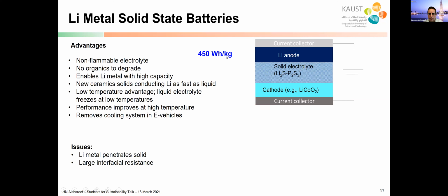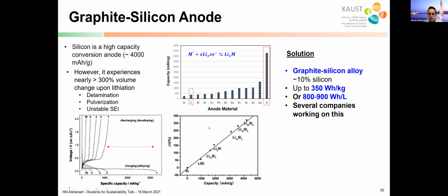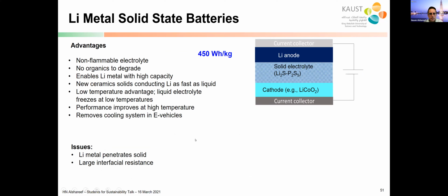Solid-state battery could give 450 watt-hour per kilogram. This is also realistic. Here you use a solid electrolyte, a ceramic electrolyte. It's non-flammable. There's no organics to degrade. And this will allow you to use the lithium. And the lithium, if you look at this, also actually, it's not in here, but it has a very large capacity as well, just like silicon, 3,000 or so. And so there are some issues with this battery: lithium metal penetration into the solid, large interfacial resistance, and you need to solve those. So nearing commercialization, like I mentioned, some big companies are working on this.